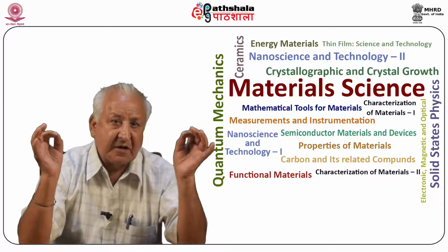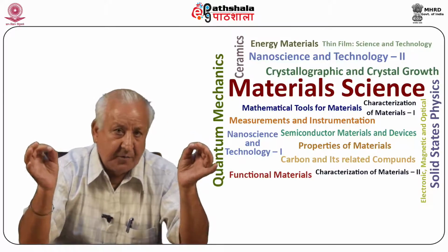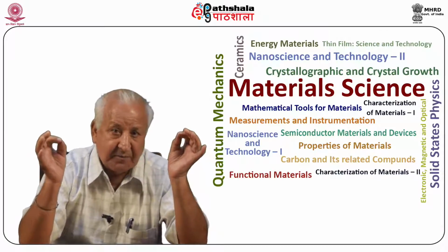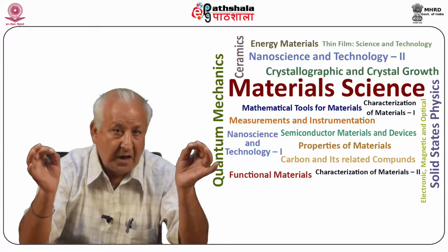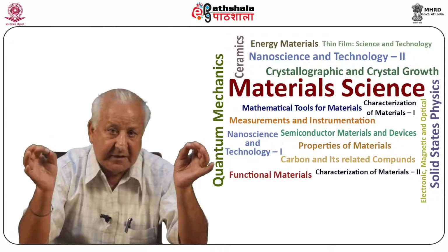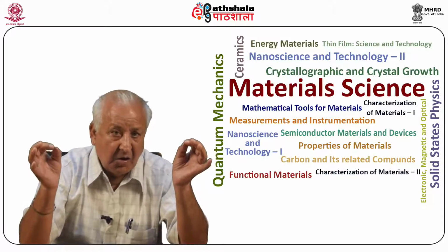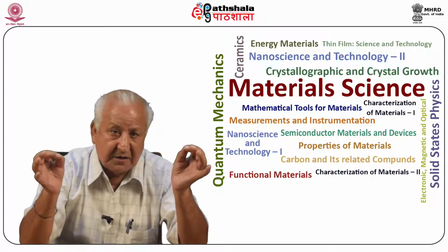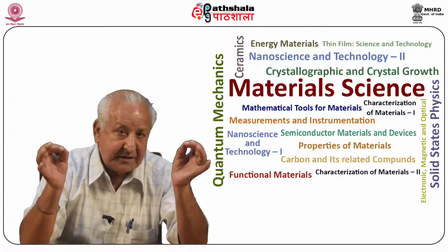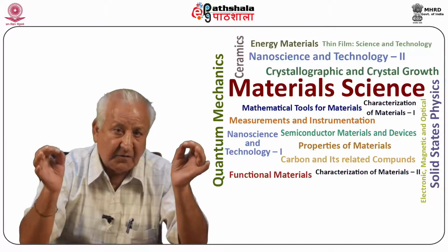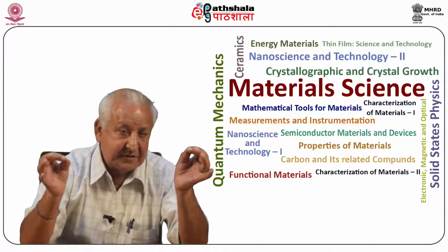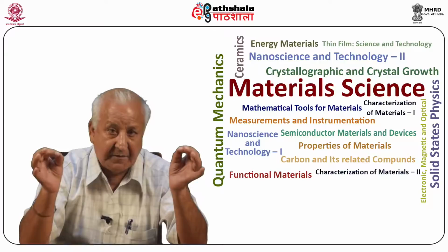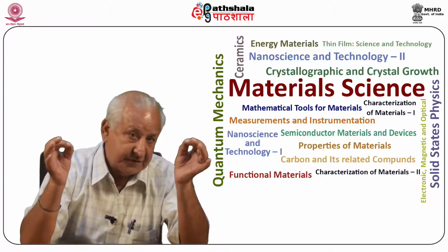Elastic deformation is caused by strains which obey Hooke's law. According to Hooke's law, atomic displacements are proportional to the applied force. When the elastic limit of a solid is exceeded, permanent or plastic deformation sets in. In many crystals, it occurs by slip. Theoretical estimates of the elastic limit of perfect crystals yield values 10^3 or 10^4 times higher than the lowest observed values.